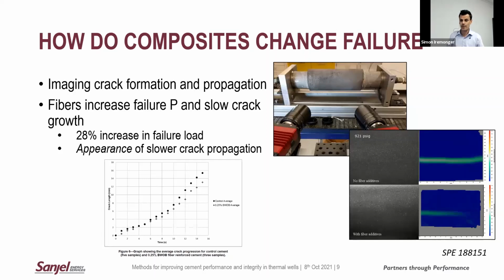And I say the appearance of slower crack propagation, anyone who's done failure analysis would know that cracks should spread incredibly quickly and certainly way beyond the speed that we would have been able to capture in the test setup that we had. And what we really think here is that there's some complex failure processes occurring that's leading us to be able to actually follow this process and see it occurring.